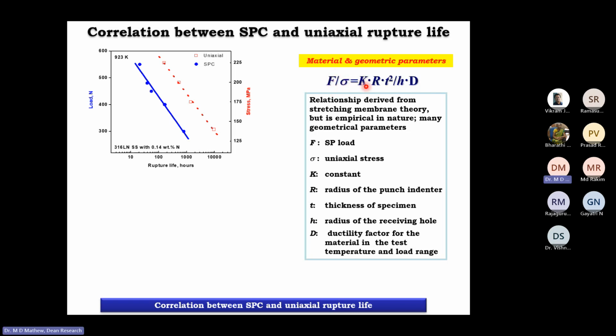F by sigma is equal to K into R into T squared by H into D. Capital F is the SPC creep load, and sigma is the uniaxial stress, which is found to be equal to some constant K into capital R, the radius of the punch indenter, into T, the thickness of the specimen, and H, the radius of the receiving hole of the indenter fixture, and capital D is the ductility factor for the material. So it's a complex relationship, but it's an empirical relationship, and it has been found to be useful for correlating the SPC data with uniaxial rupture data.